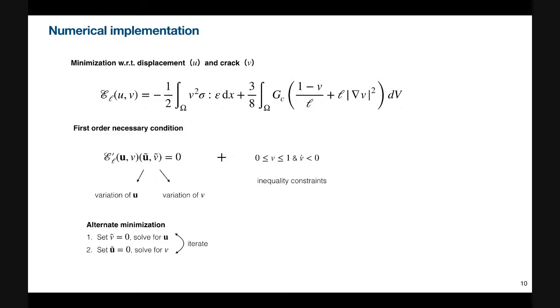And taking advantage of the fact that this energy functional is biconvex, it's convex in U and convex in V, we do alternate minimization. So we first solve for displacement by setting the variation with respect to v equal to zero, and then we solve for v by setting the variation with respect to displacement equal to zero. And we iterate until it converges.